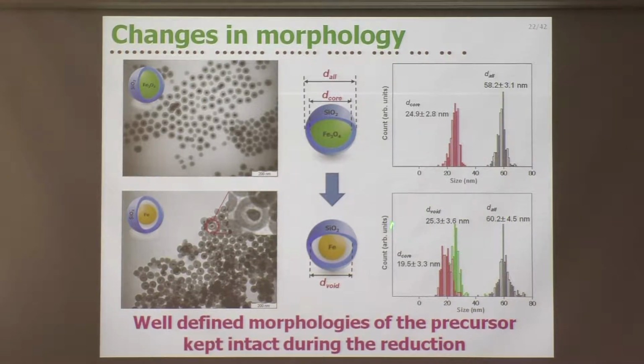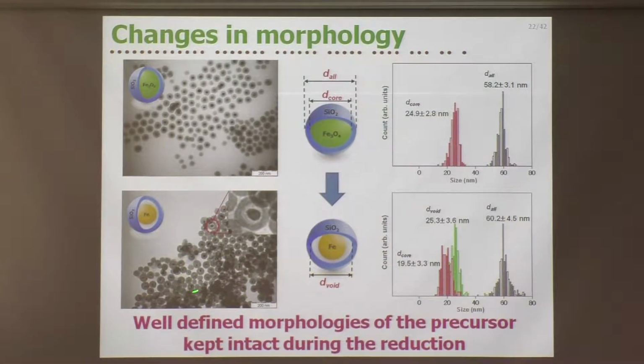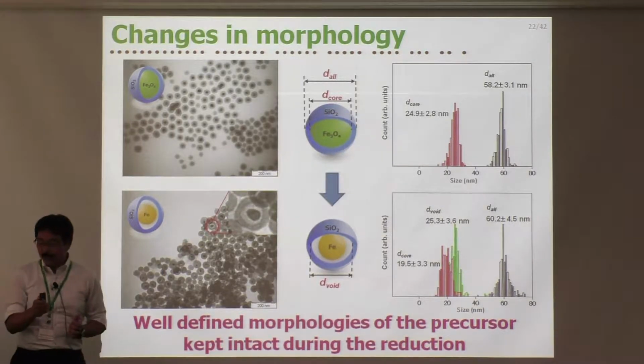The size of the void is about 25 nanometers, which is in good agreement with the size of the core before the reduction. So as I explained, with this reduction method, we can get nice alpha iron nanoparticles with particular shapes.